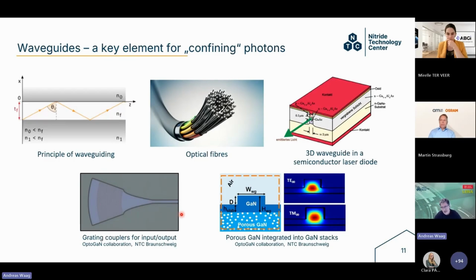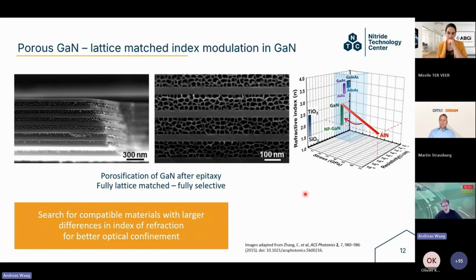And this is one of the issues. If you stick to material which is compatible, which is more or less lattice matched, then the difference in index of refraction is relatively small, and therefore the confinement is relatively small in comparison to electron confinement in microelectronic circuits, and therefore there is always this spread out wave function which is running also partially outside of the waveguide. This is the evanescent part of this mode, and this is what has to be taken care of. And therefore, there is a search for a compatible material platform with larger differences in index of refraction. And just to show one example is porous gallium nitride.